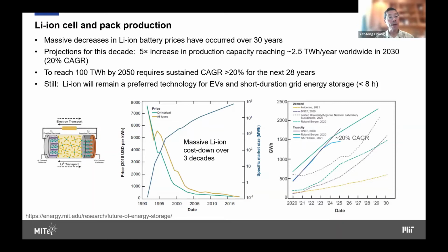And when we compare that to the need for 100 terawatt hours by 2050, this implies that the compound annual growth rate would need to be sustained at greater than 20% for the next 28 years. And that points out how heavy a lift it is to do all of grid storage with lithium ion, even if the cost continues to decline and we find lithium ion chemistries that are lower cost.